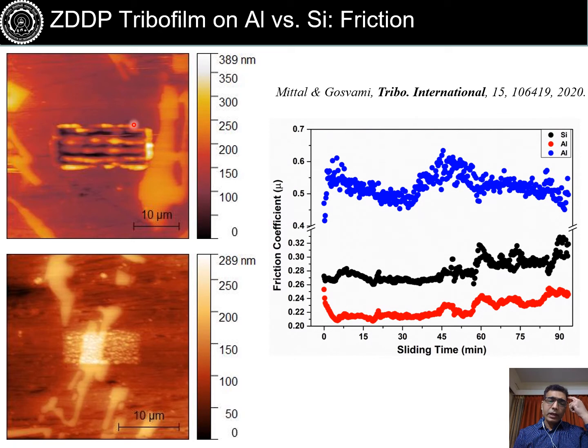Another interesting observation we made was when we are sliding far away from the silicon, purely in the aluminum matrix, we see that film did not develop. We see continuous wear of aluminum. So we thought that it could be due to the fact that silicon is somehow affecting the mechanical property of the neighboring aluminum matrix with respect to a region which is away from the precipitate. But we did nano indentation and we see that there's not much mechanical property variation in aluminum matrix closer to the precipitate or away from the precipitate. So it has to do with something else, which can be related to small chemical changes in the substrate, but we have not yet fully resolved that, and we are still working on it.